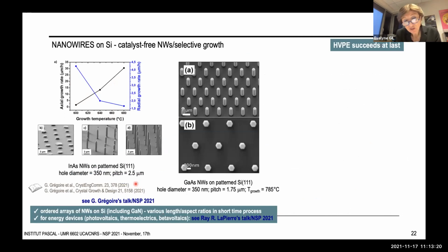Finally, the solution was found to grow III-V nanowires on silicon by HVPE without gold. The idea was, in fact, to prepare the silicon surface, not with a gallium chloride or indium chloride atmosphere at low temperature, because that doesn't work, but to saturate the silicon surface with arsenic atoms under arsenic atmosphere, which will facilitate the further nucleation of the III-V.